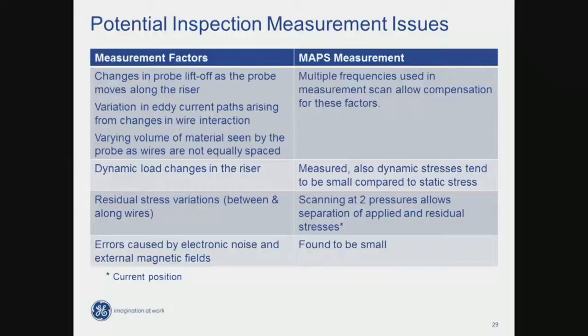But what we've found, irrespective of OEM, is that the residual stress distribution is actually a variable in the pipe. And in fact, the variation in residual stress as you go along a wire, or from wire to wire in the same pipe, is not a small number. What we found is that that variation is comparable to the change in signal due to a wire break. Remember, we measure the total stress, so we've got residuals and externally applied loads.